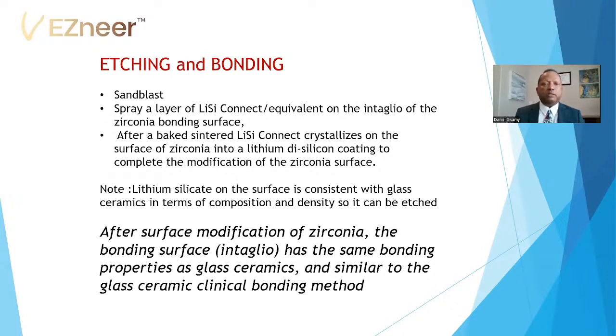So basically what you want to do is sandblast the intaglio surface, okay? And you can do it by adding the 2 methods of additive process of using a spray glaze. You spray it on the intaglio surface, or you use a very thin slurry of the glaze. You fire that in your ceramic oven, and then you use the conventional techniques of etching with the hydrofluoric gel. So after the modification of the zirconia, the bonding surface has the same bonding properties as glass.